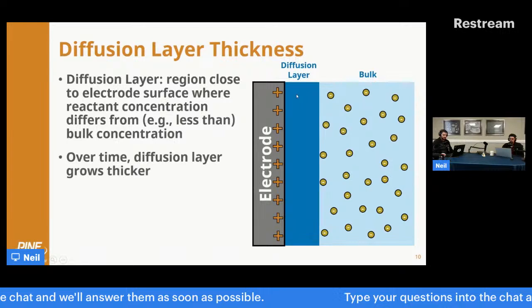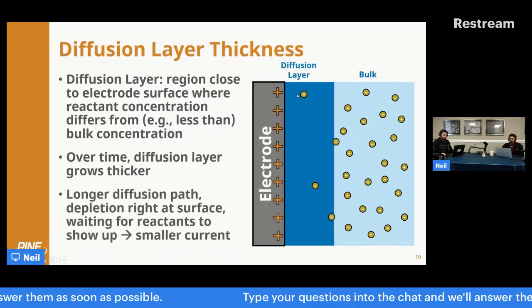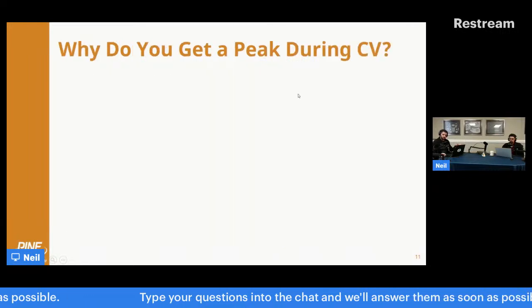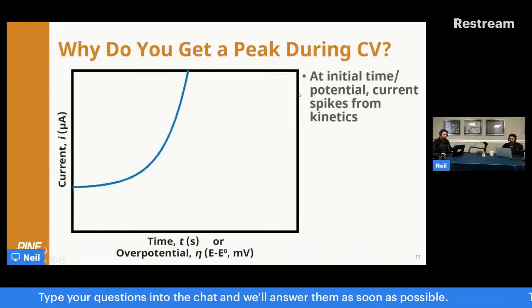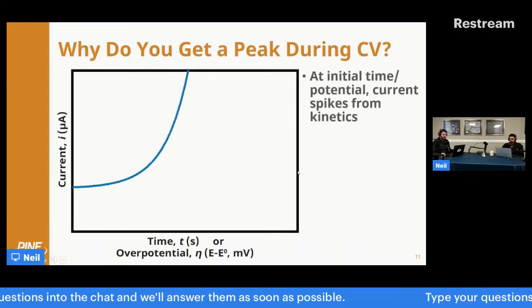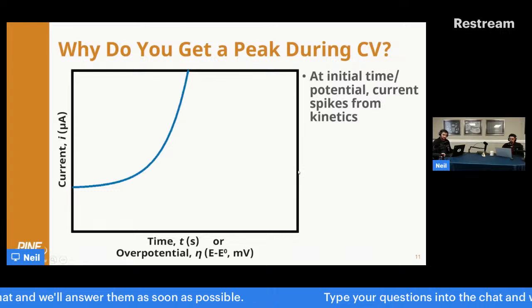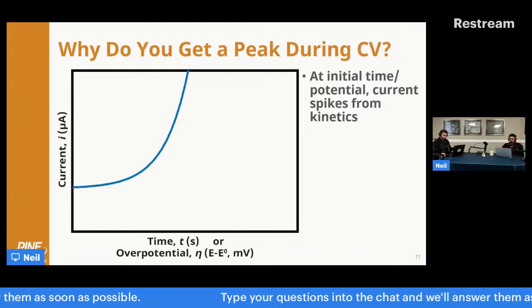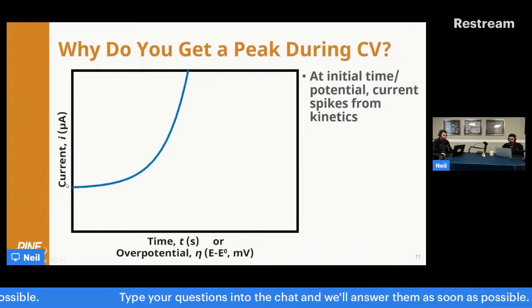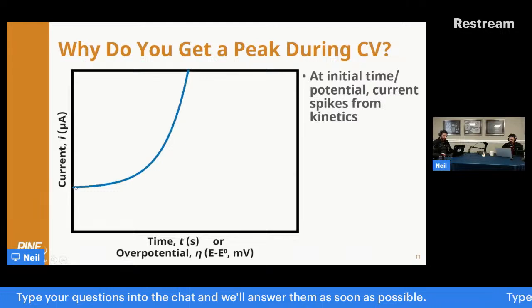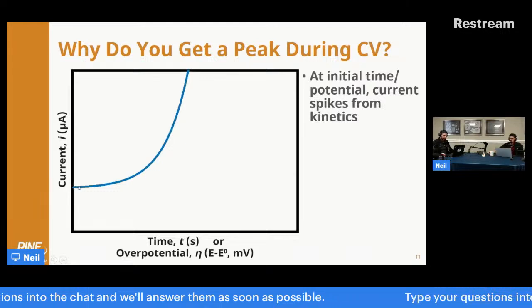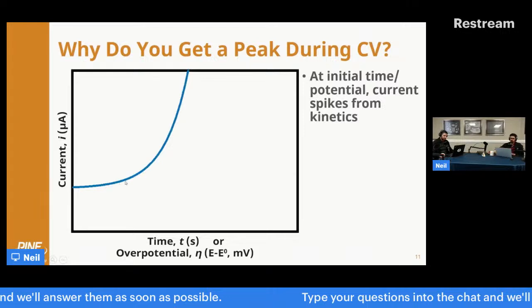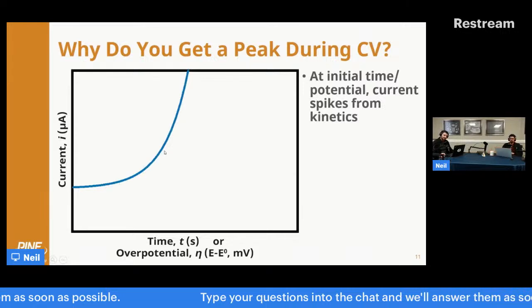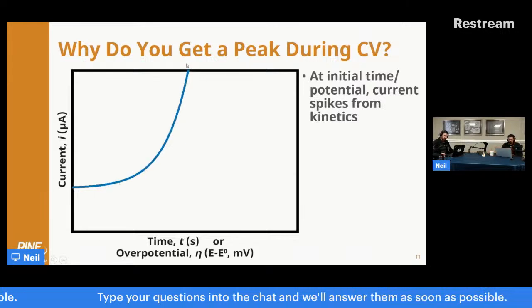I'm going to skip this a little bit because I want to show you the peak phenomenon. As I said, stuff takes longer to get there, so you get less current, but why do you get a peak? If you're scanning in a cyclic voltammetry experiment or LSV, a linear sweep, you're moving the potential in time at some rate. As you do that, you increase your overpotential. Butler-Volmer kinetics dictates that I should have an exponential increase in my current.